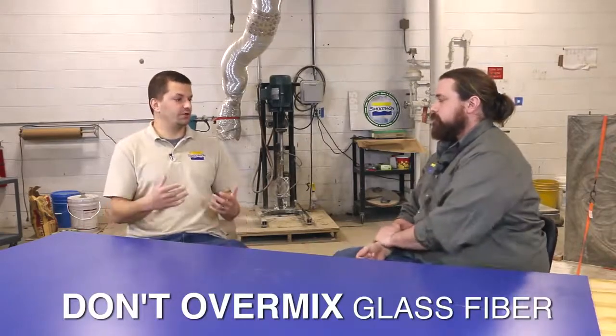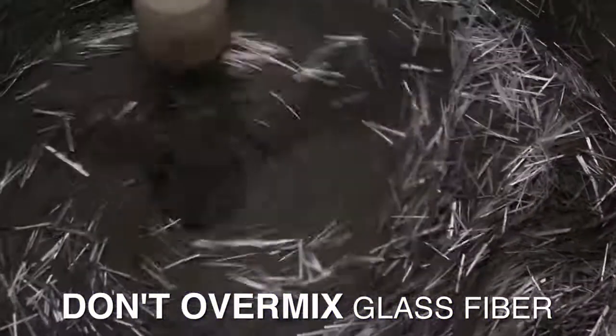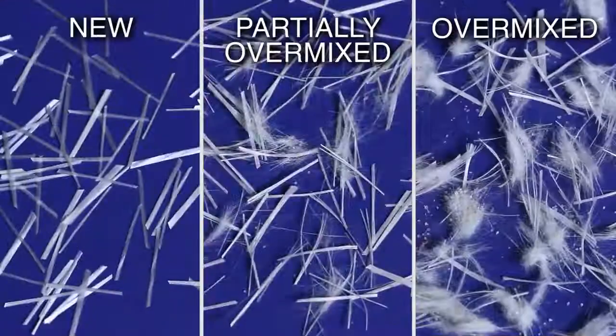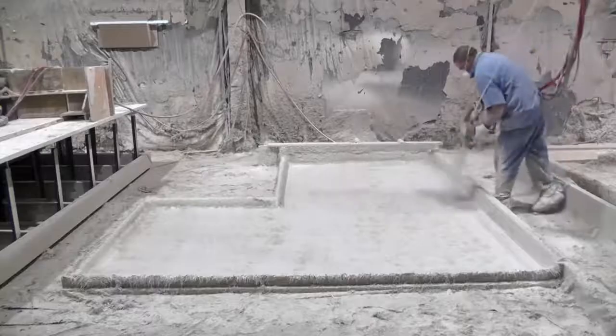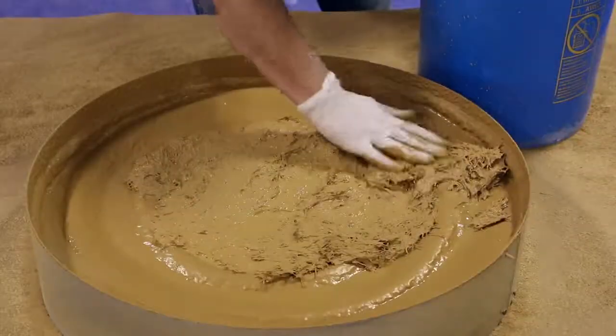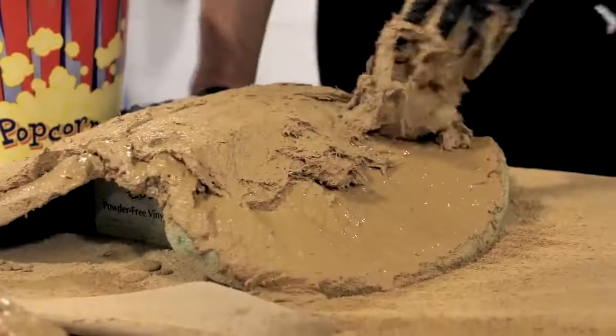But the important thing is not to over mix it, because if the glass fiber gets over mixed, you break down the fiber, it could filamentize and bird's nest, causing workability and placement problems, but more dangerously, failure of the glass over long term. Yeah, strength issues over time, right? So after that's all mixed together, you're ready for placement, whether it's done through a gun or by hand, which is most typical and what you probably would have seen through most of our videos.